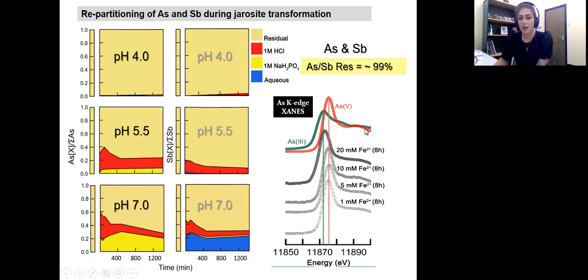and I didn't show the result here, but when we analyzed our samples with the same analysis in the synchrotron, we observed that antimony 5 stayed as antimony 5 over the course of mineralogical transformation, and it didn't change. So this experiment that I conducted was conducted in a very pure system.